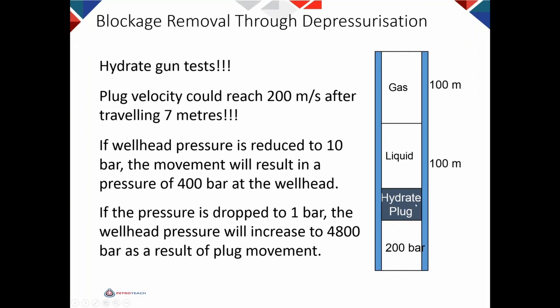This plug will melt, as I mentioned, from the wall because heat transfer is radial, and that will release this plug, and this plug, because of the pressure here, will move upward, shift the liquid, compress the gas, and exert the pressure to the wellhead. That pressure could be 400 bar. A lot of wellheads can withstand 400 bar. But if you reduce the pressure to 1 bar, the pressure before stopping the movement of the plug will be 4,800 bar, and no wellhead can stand that pressure. So you need to be very careful with plug movement.